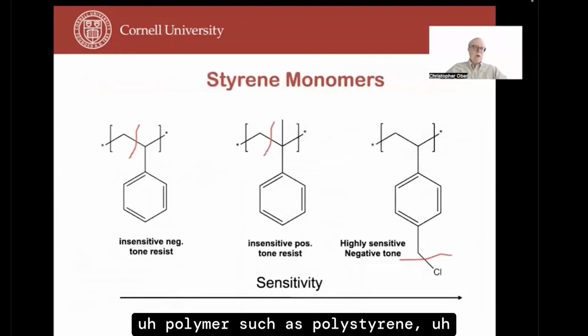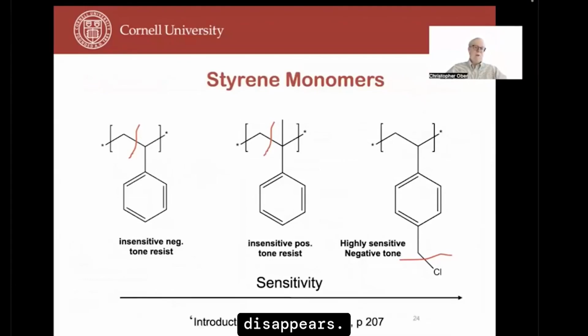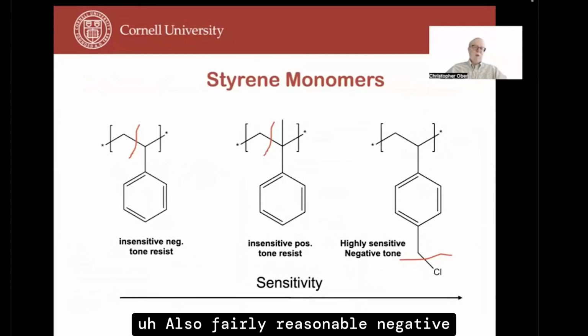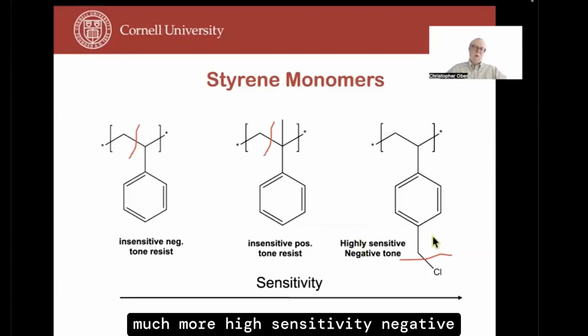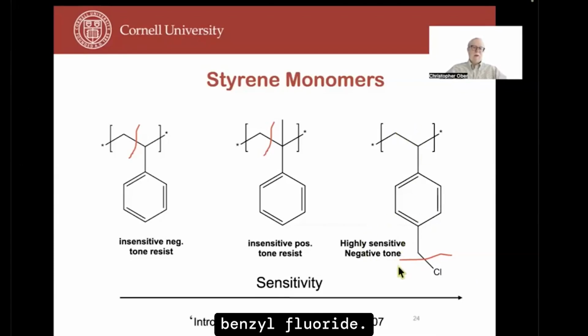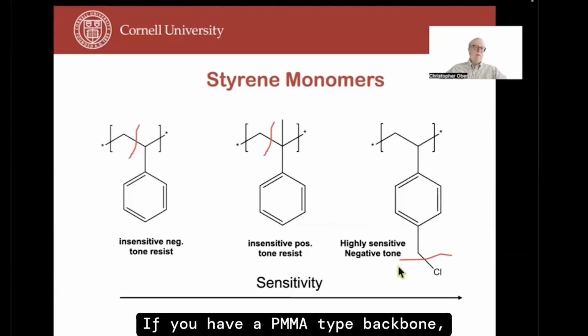A polymer such as polystyrene, so those were positive tone resist because they unzip, the polymer disappears. Also fairly reasonable negative tone e-beam resists are based on polystyrene. You can cause cross-linking, but you can enhance the change in solubility of the material by tinkering with the structure. Something that forms a much more high sensitivity negative tone resist is this polyvinyl benzyl chloride. So if you add that as a moiety, it'll tend to go negative. If you have a PMMA type backbone, it'll tend to go positive.